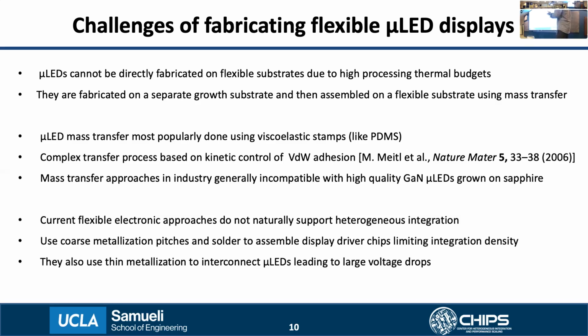The other set of issues in making these kinds of displays has been that current flexible electronic approaches themselves do not naturally support heterogeneous integration. This is because they are typically based either on using printing techniques or some kind of evaporated metallization, where the metal pitches are typically coarse, and also the different components such as microcontrollers, driver ICs, and so on that are needed for a fully working display are typically assembled using flip chip bonding with some kind of solder, which limits the achievable interconnect pitches as well as the pad pitches. They also use thin film metallization or printed interconnects, which have a very high series resistance that can lead to large voltage drops while driving large arrays of micro LEDs.